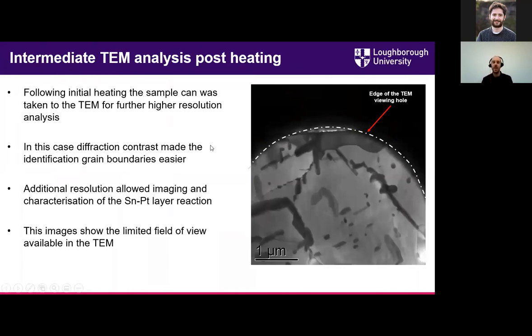Just to demonstrate what it would be like looking in the TEM versus looking in the SEM, this was a view from inside the TEM. You can see that our field of view is much reduced, and with that, we lose a lot of context as to what else could be going on in the experiment.